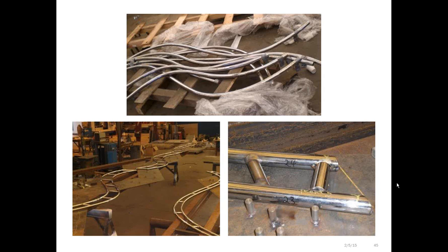You'll see down in the bottom left-hand slide that some of the units, the flat units, have been welded up. I'll talk in a minute about the welding procedures. You do need to pay more attention when you're welding this material than when you're welding a straight-up austenitic. The picture on the bottom right shows you units that are on the fixture getting ready to be welded one section and the next, and you can see the broader weld prep than we might normally use for an austenitic.